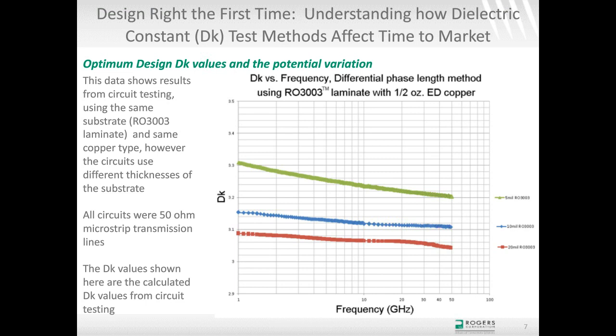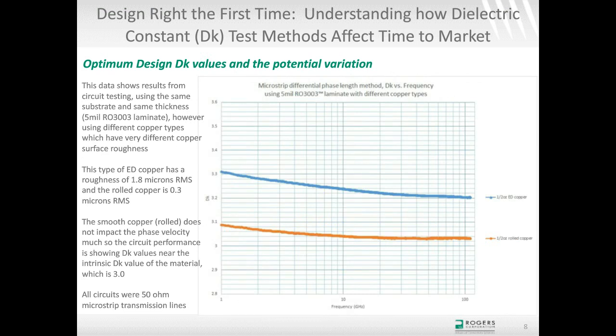Now, if you actually made a circuit that was thicker, let's say about 50 mils thick, then that curve should settle in right about 3.0 because the intrinsic value of the substrate is 3.0. Once the copper planes are moved far enough apart, in the case of a thick laminate, then the surface roughness does not affect the wave velocity anymore, and you're really looking at the intrinsic value of the dielectric constant of the material.